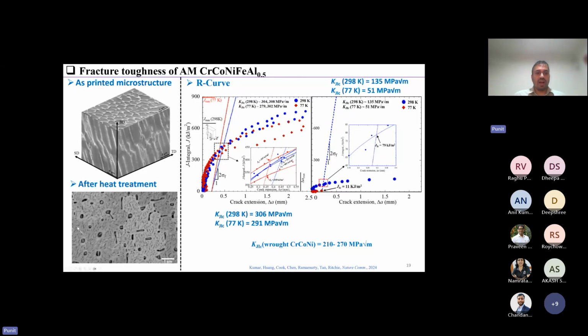So the fracture toughness is actually even higher than what we see in wrought CrCoNi, which shows fracture toughness of about 200 to 270 megapascal root meter. So to get an idea of the extent of fracture resistance in this material, we also did some heat treatment to dissolve these B2 phases on the cell boundary and have these nano precipitates of B2 phase inside the matrix.